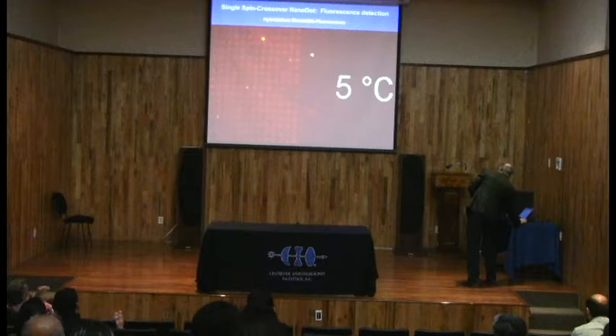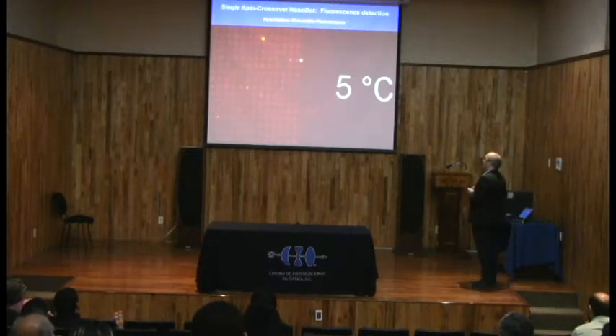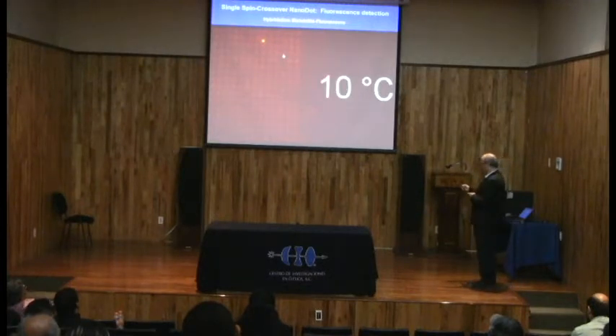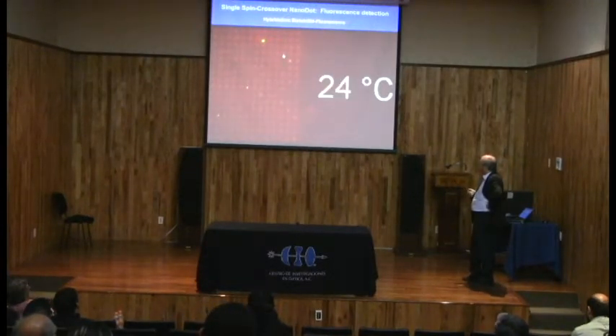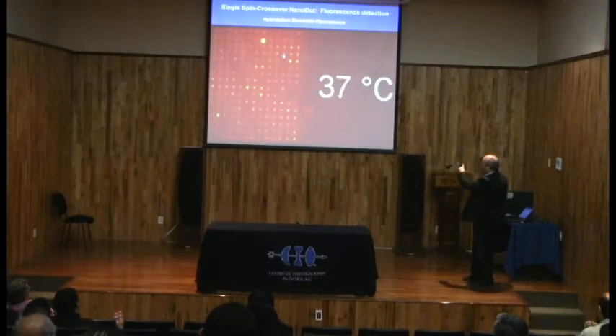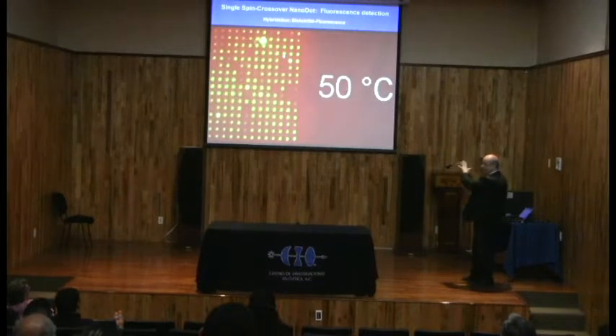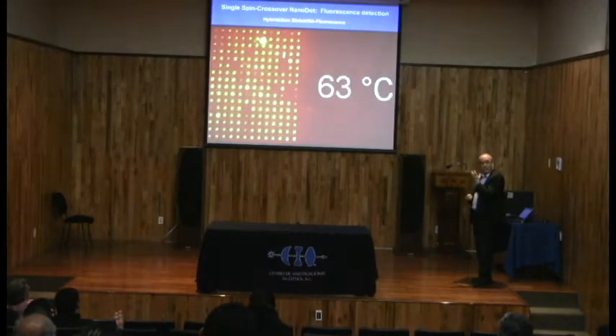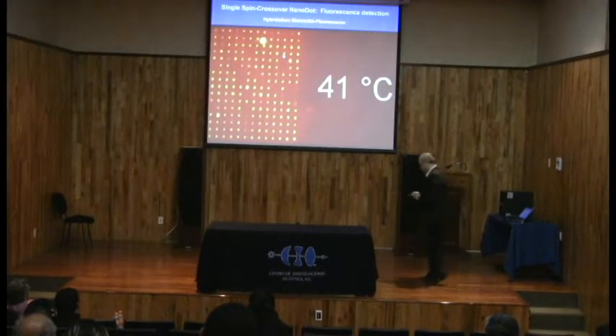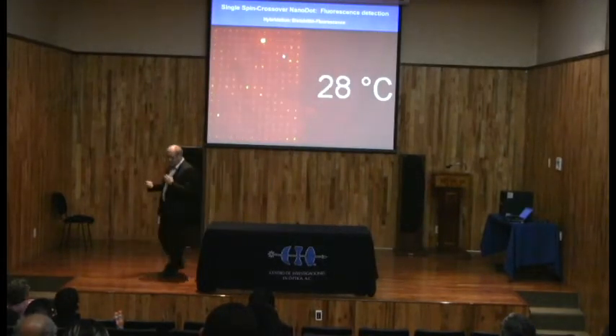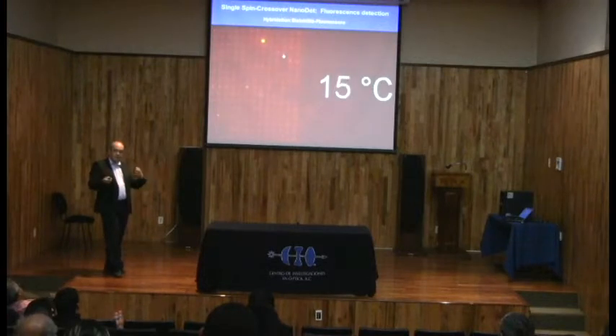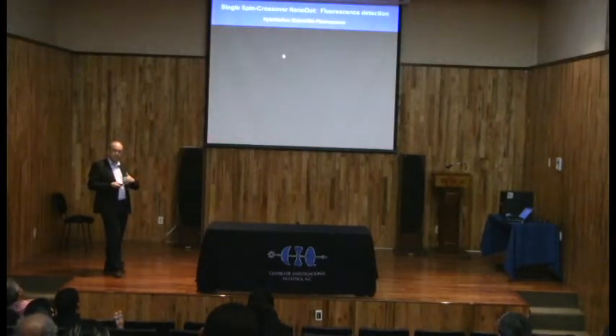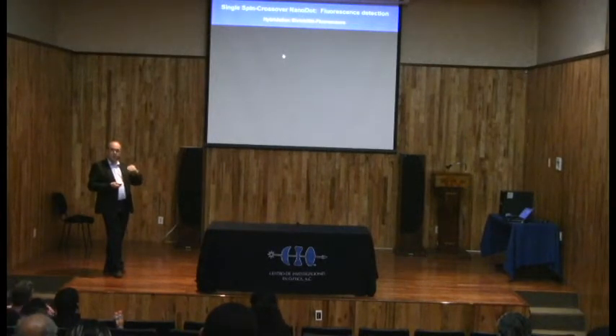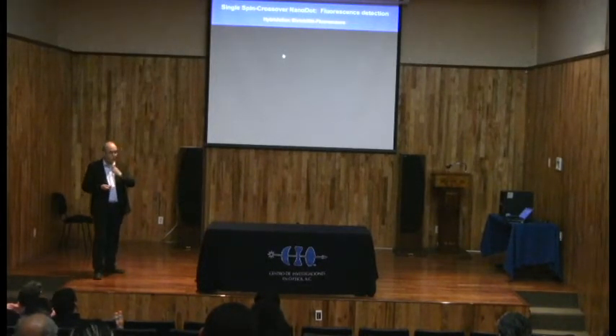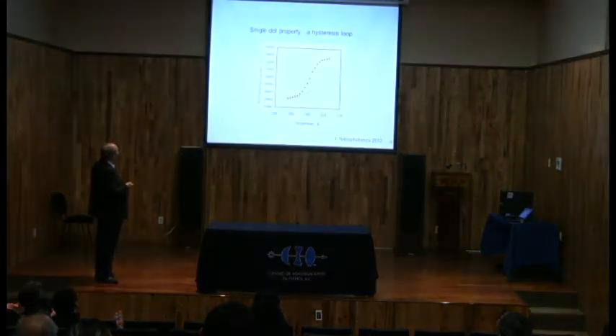So you see that if now we increase temperature to have the spin crossover, around 50 degrees, when we have the switching from low spin to high spin, light is released, so it's not absorbed, so we have quenched the luminescence through the spin crossover. Okay, so that means that a synergetic effect between rhodamine and spin crossover is possible. You see that by temperature, by having spin crossover, we can quench the luminescence, and then we can control the luminescence by switching the system by temperature.